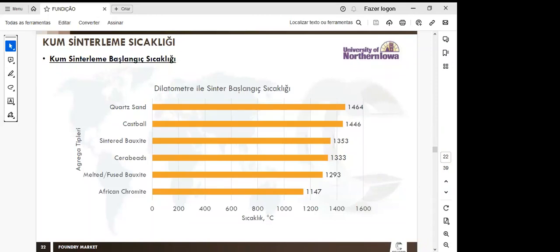Here we have the results of the starting temperature of sintering in the foundry sands. The results are organized from the highest temperatures to the lowest. Here we have silica sand and Castball. They presented the highest initial sintering temperatures, while sands such as fused bauxite and chromite had the lowest initial sintering temperatures. It's very important when we think about penetration defects and the durability of the sands.